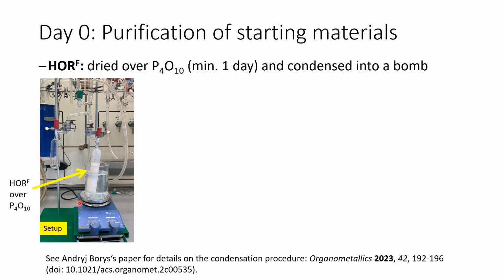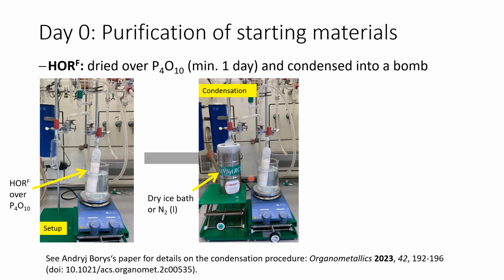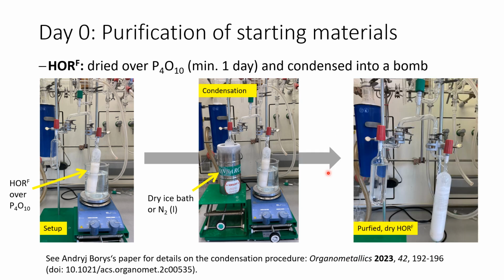Then we perform a static vacuum condensation to condense our now dried alcohol into a new storage vessel. The setup for this is shown here. We attach the condensation bridge as well as the new storage vessel to our vessel with the alcohol and the drying agent. Then we do a freeze-pump-thaw cycle on the alcohol. In the next step, we condense it over by using a dry ice bath with CO2 and isopropanol, or by using liquid nitrogen. More details on this condensation procedure can also be found in Andryj Borys's paper in Organometallics. At the end, we have an alcohol which is now very pure and dried and ready for our reaction.